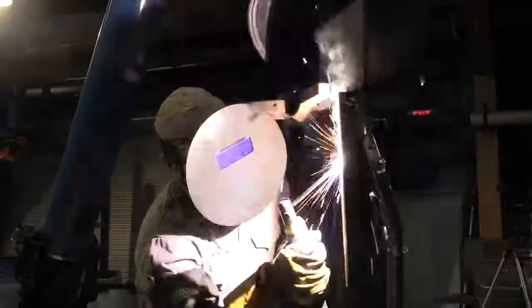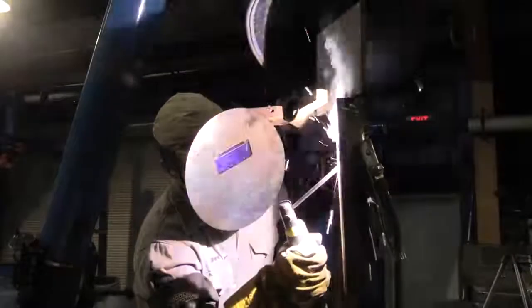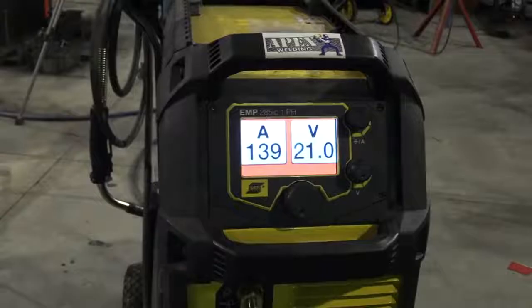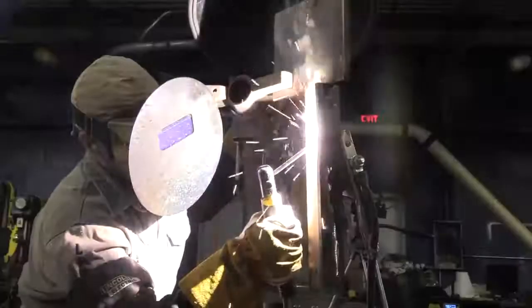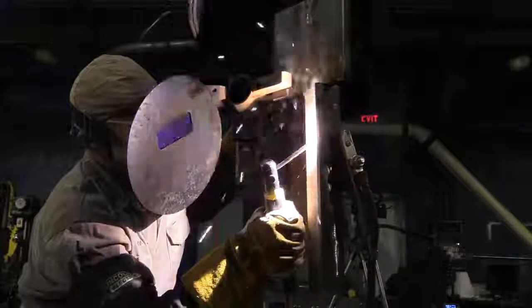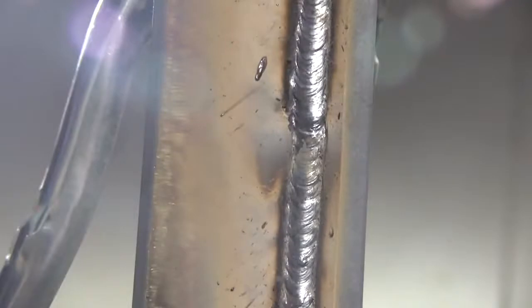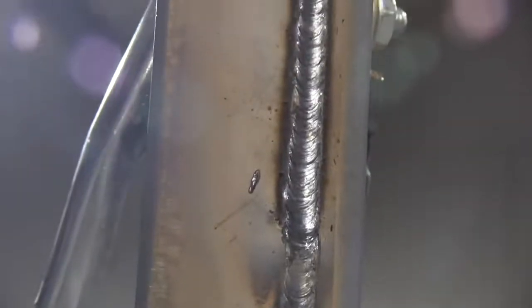All right, our restart technique is to avoid any arc strikes. So Andrew's going to strike up ahead of the crater by about an inch, and you see it deposited some spatter and some stuff there, and he's just going to weld right back over it. That's the technique to avoid arc strikes. Make sure to weld back over any arc strikes that you do happen to have. It also lets the 7018 heat up just a little bit, and prevents porosity there on the tie-in. And you see that's the restart, the tie-in right in the middle there.